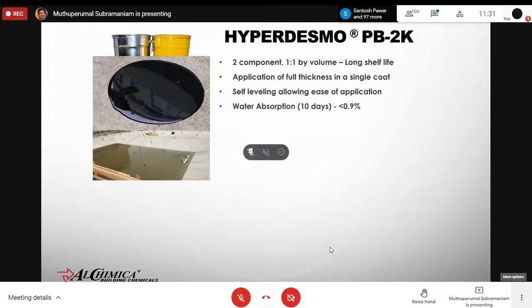The most important point here is the water absorption. Generally in liquid applied systems, we found that the water absorption used to be very high because of the filler material we add to the coating. Here, bitumen is added as a filler material with polyurethane. The water absorption is as low as 0.9%, which is accepted by the international code ASTM C836.